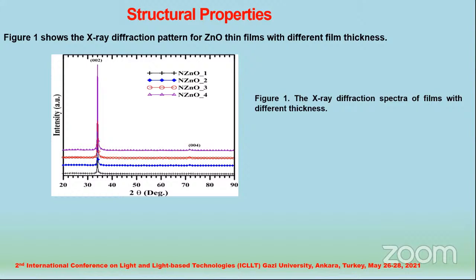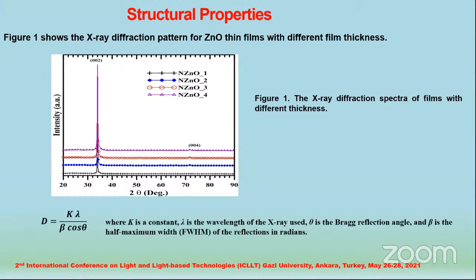The grain size of the crystallites in the films is calculated from the X-ray diffraction data by using the well-known Scherrer formula, where K is a constant, lambda is the wavelength of the X-ray used, theta is the Bragg reflection angle, and beta is the half maximum width of the reflections in radians. For calculations, the K constant is taken as 0.9.